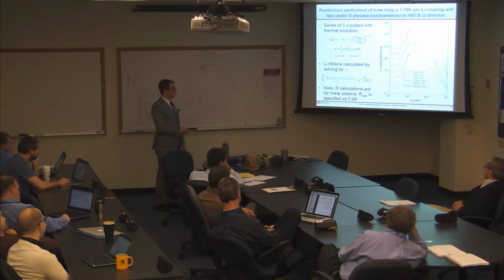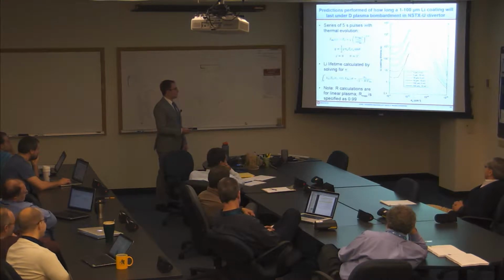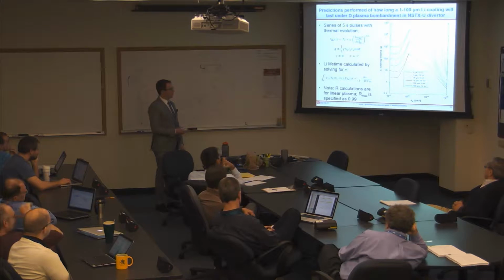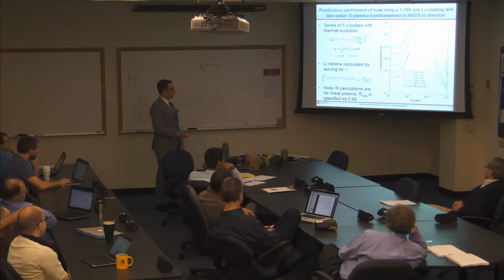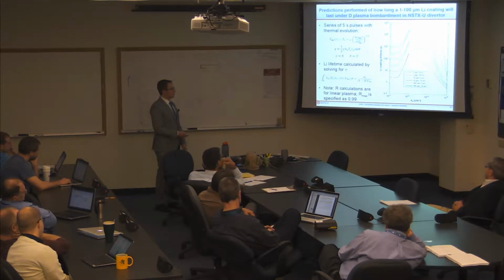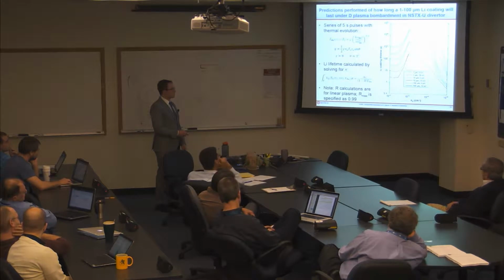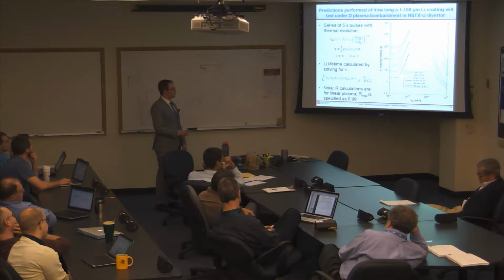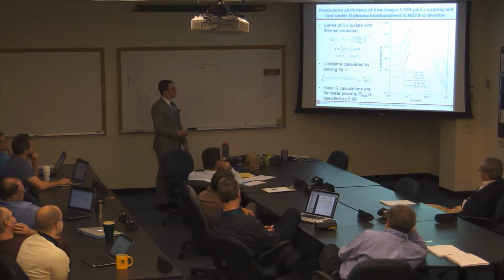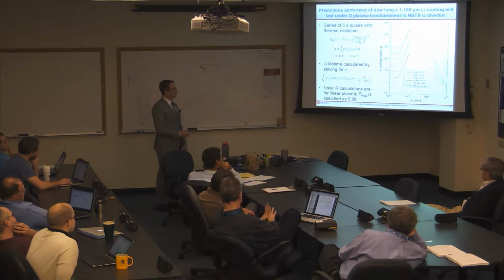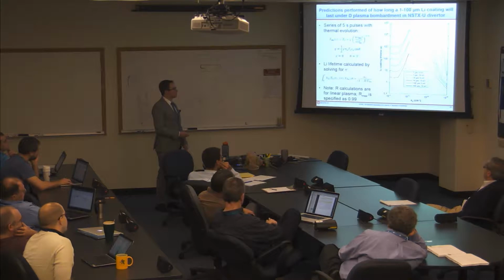So this is the predicted lithium coating lifetime as a function of density on the horizontal axis, and two different temperatures: 5 eV is the dashed lines, and 10 eV is the solid lines. The different coating thicknesses were 1 micron, 10 microns, and 100 microns. The typical NSTX-U divertor parameters you expect are about 10 to the 14 to 10 to the 14 per centimeter cubed. If you follow this up, you get something right in here for a 1 micron coating. In this range, at least, the coating lifetime is pretty linear with the thickness. So the lifetime increases as the thickness increases by an order of magnitude.